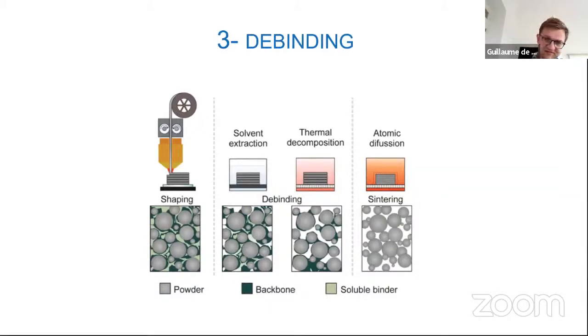So the first step is just dipping the part in acetone, which will remove part of the binder. As you can see in the picture, the binder composition we have are usually at least with two different components, sometimes a bit more. And one of them is what we call a soluble binder. It's going to be removed by the solvent, and the other one is what we call the backbone, and it really needs to be burnt out.